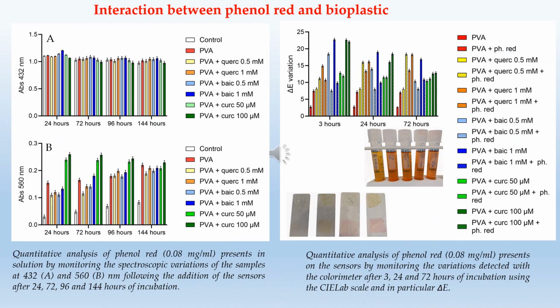Then we tested the sensor capacity to detect the presence of phenol red in solution. Spectrophotometric analysis of the supernatants taken from the test tubes containing the different bioplastics immersed in a 0.08 milligrams per milliliter solution of phenol red highlighted over the days a slight change in the absorbance values at 432 nanometers with all the substances tested, but at the same time an increase in the absorbance values at 560 nanometers was found in all the test tubes, which highlighted the color change from yellow to pink, much more marked in the presence of curcumin and completely absent in the test tube containing only phenol red in the absence of the sensor. The color shift of the sensors towards pink was confirmed and quantitatively analyzed by colorimeter study.